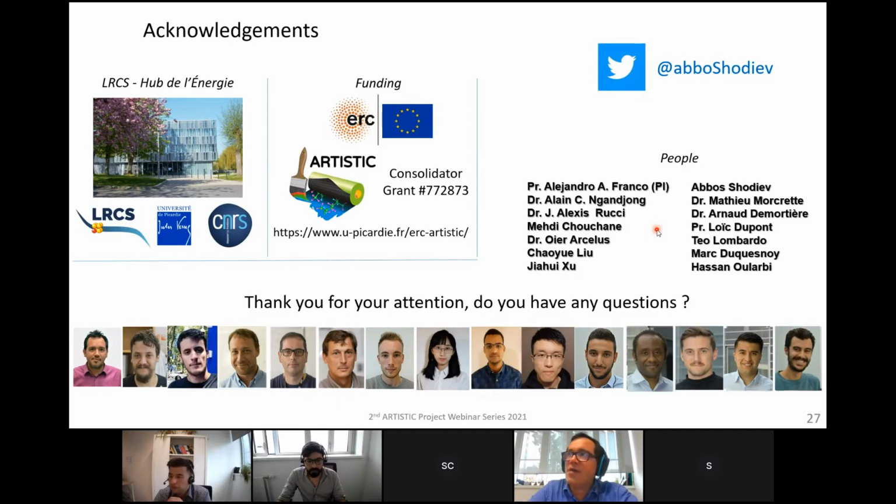And here is another comment: the overall contact angle is an input parameter for the lattice-Boltzmann model, while in reality you may have different contact angles for carbon, for binder, and for active material, correct? Oh yeah, sure, of course. The overall contact angle, you just put a drop, measure it, and it's the input. But inside the structure it might change, and that isn't taken into account.